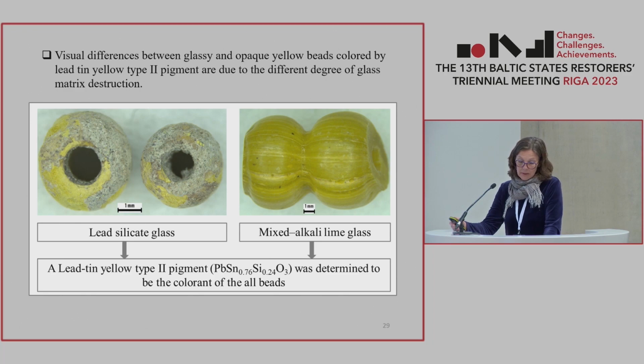In a dry environment, any type of glass does not change for a long time. The chemical destruction depends on the chemical composition of the glass matrix and its interactions with external factors, the most important of which are water or a humid environment. Lead glass is quite soft, therefore it is relatively easily mechanically damaged, and such glass is easily affected by destruction, especially when the environment is acidic. The analysis of chemical composition and structures of beads provides important information on the technological features of the production of glass beads, but in my opinion, too little research has been done on the chronological description of bead production.